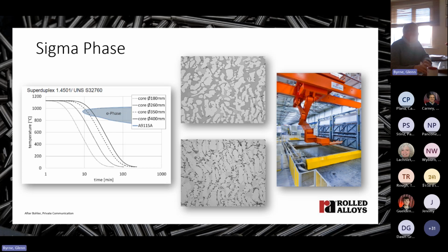The third mechanism is it can form as a consequence of repeated thermal cycles in the sensitive temperature range. And the time that's spent in this temperature range is cumulative, and the steel remembers its thermal history. So if you heat it up to the temperature range, spend a small amount of time, cool it down, heat it again in that range, spend a small amount of time, cool it down, all of those times at temperature become additive. And if they become sufficient in total to enter the phase field, then you'll get sigma.